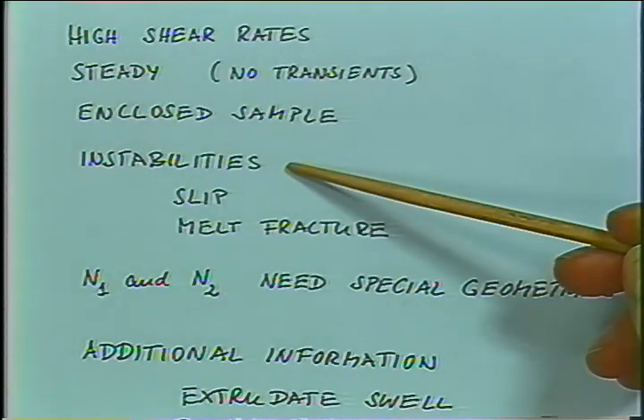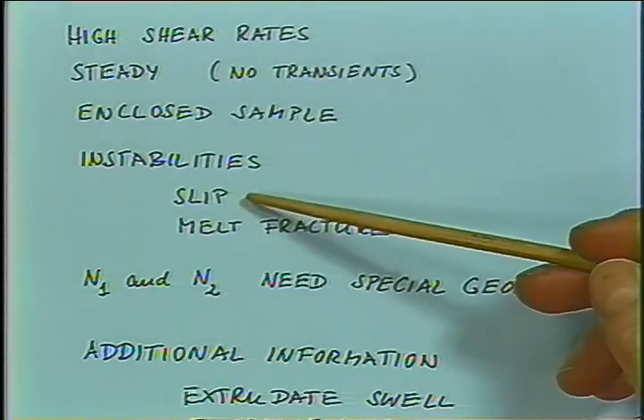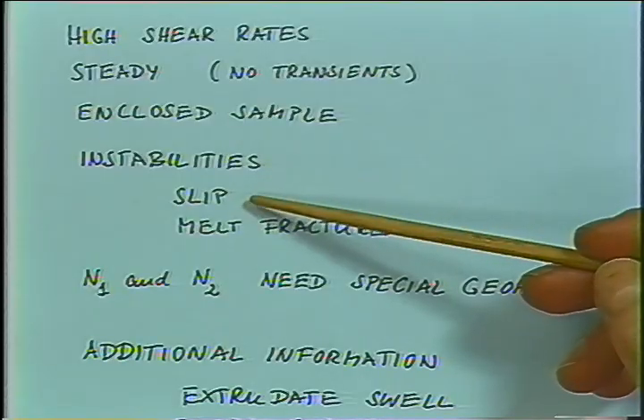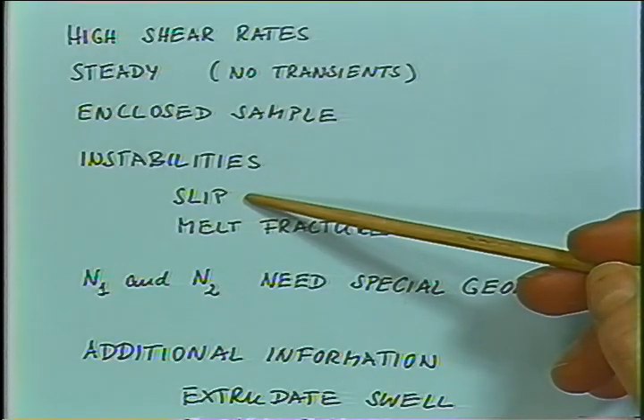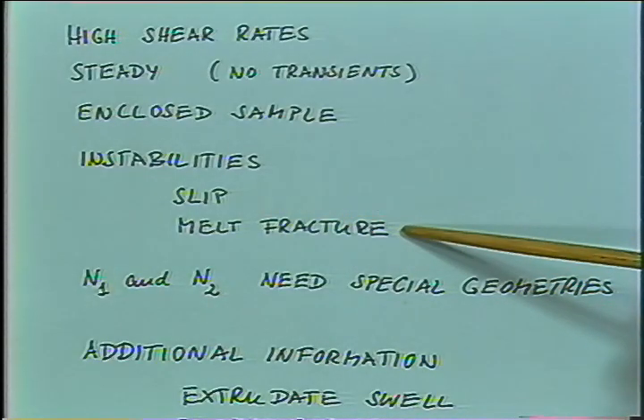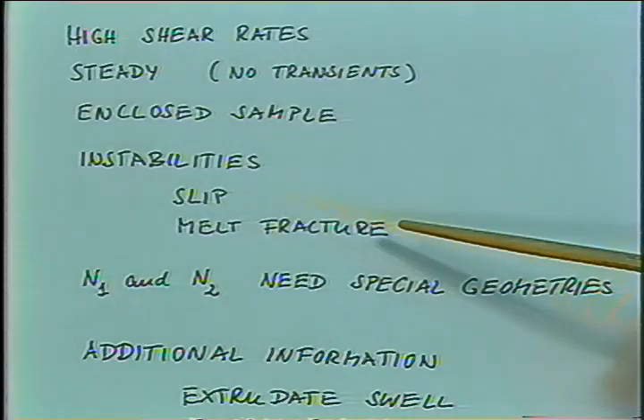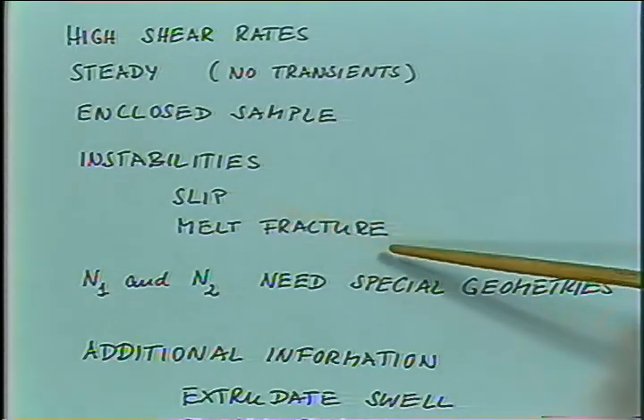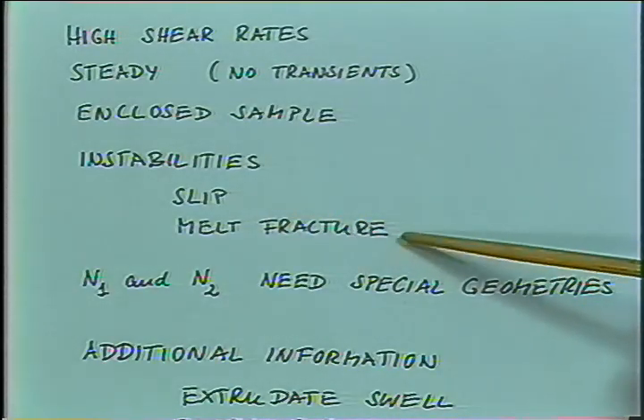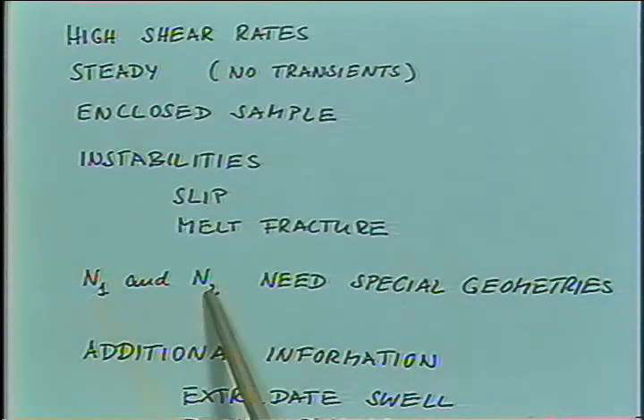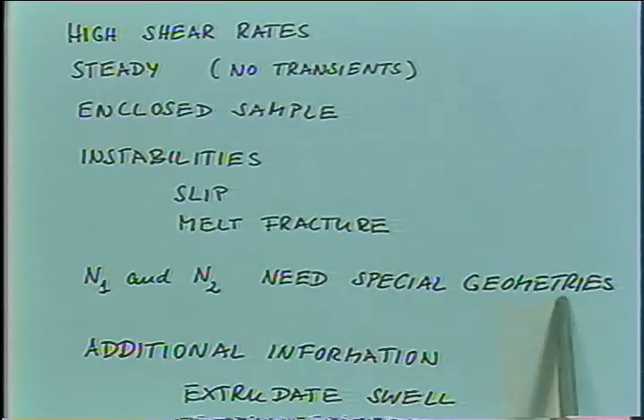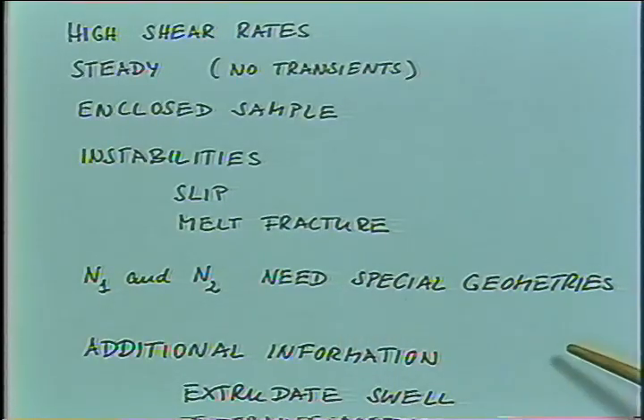Instabilities are interesting to study. We can use capillary rheometers to measure slip velocities and the onset of slip. And we can study the onset of melt fracture, which might have its origin in slipping, but more often it's a more complicated phenomenon. N1 and N2 under steady shear conditions can be measured, but that measurement would require special geometries to succeed.